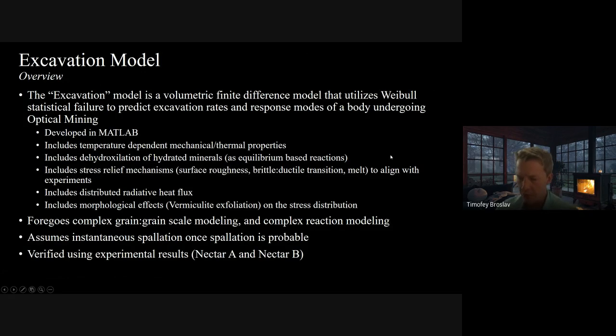So the model that was a big portion of this work was developed based on the experimental results from the test setup that I described. This excavation model was developed as a volumetric finite difference model and utilized Weibull statistical failure to predict excavation rates and response modes of a body undergoing optical mining excavation. So this was developed in MATLAB, used temperature-dependent material properties, included a variety of dehydroxylation reactions, as well as stress relief mechanisms due to surface roughness, the brittle to ductile transition and melt, in order to align better with experimental results. It included a distributive radiative heat flux as the boundary condition, just because the beam that we were working with wasn't just a beam of a single irradiance. It had zones, like a concentric circle, think of it like that. And so I had to make sure to incorporate that in the model.